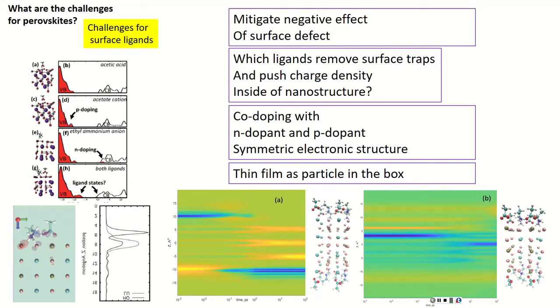And then there are, by now, pretty standard procedures to run electron dynamics and follow charge distribution as a function of position. So in these diagrams, the x-axis is time and the y-axis is position z across the slab. So at time zero, in both cases, the excitation is distributed in space between ligands, approximately in the space in between. Well, not always, but it was an attempt. And as time passes by, the question is whether both electrons and holes will stay in the slab and keep this lowest excitation emitted, or either electron or hole will migrate to the layer of ligands and quench the luminescence, make the state dark.